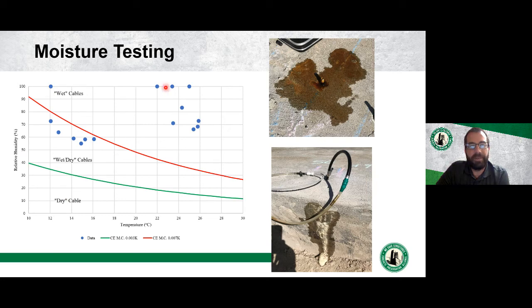These three dots, where they're at 100%, that's where there's just standing water in the tendon. So you can see here, we've put pressure on this tendon and water is just spurting out of the duct, and here water is coming out of the anchorage. But then you can see, definitely, 70 to 90% RH is coming out of those tendons. So there's a lot of moisture along those tendons.